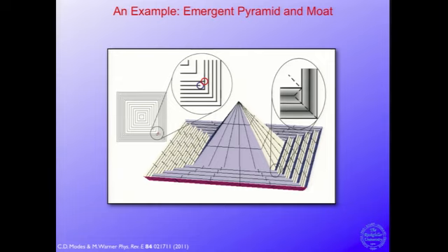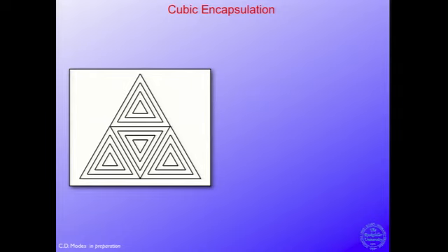They nucleate this little moat sort of texture around the pyramid. And because of the need to concentrate that Gaussian curvature at the new points, you can no longer really spread out the bend energy. And so you get a proper cone, a sort of quasi-isolated proper cone. You can imagine doing things a little fancier.